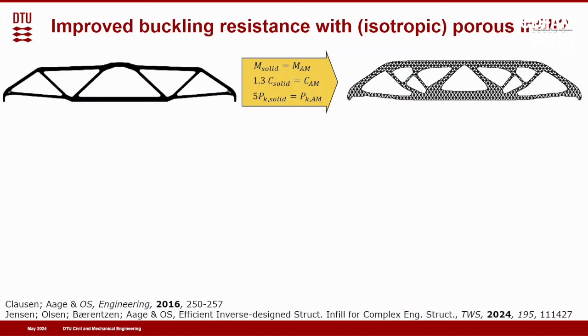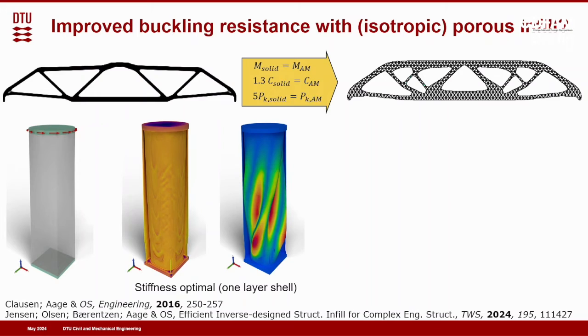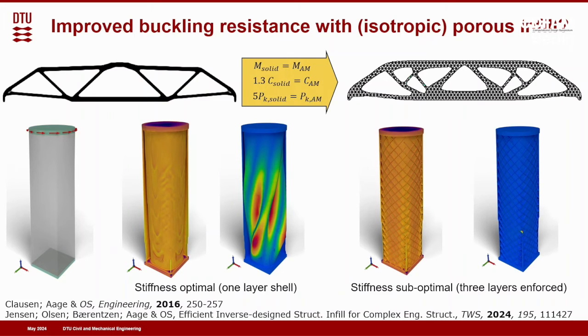So that might be a motivation: use microstructure to get better stability. And Peter also has an example where we took a famous 3D test case, Lotte Tower, where we have torsion on a box that is square in the bottom and circular in the top. In that case, if we just have one layer, which is the optimal one, we just have a shell like a pipe, but it has a very low buckling resistance because we will have these global buckling modes. If we insist on microstructure, we will again decrease the stiffness, but in this case increase the buckling resistance. The buckling will now be a local one. You see it in the very bottom here somewhere. So this might be a reason for microstructure.